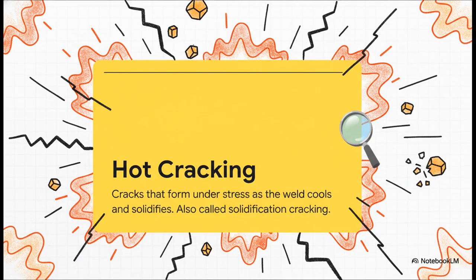And then you've got the other big villain, hot cracking. This happens at the absolute most vulnerable moment, when the weld is cooling down, but it's still kind of slushy, not quite solid. The metal is shrinking, and that creates stress. And if that stress pulls apart the delicate, crystallizing structure before it's fully solid, bam! You get these catastrophic cracks running right through your beautiful new weld.